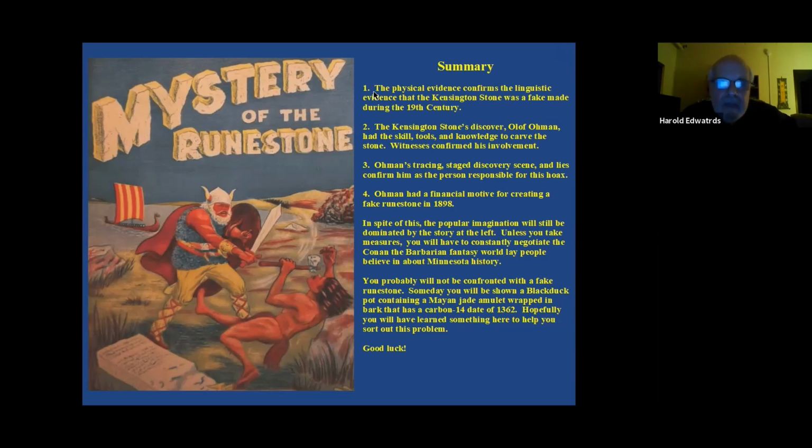stucco layer. And I suggested that they get a carbon-14 date of the stucco layer. Stuccos and mortars can be dated by carbon-14 because what you have is lime, which is basically calcium oxide that's mixed with water, that when it dries out, it absorbs carbon dioxide from the air to become calcite again. And so you would analyze that calcite, the carbon dioxide in that calcite, for the carbon-14 signature.